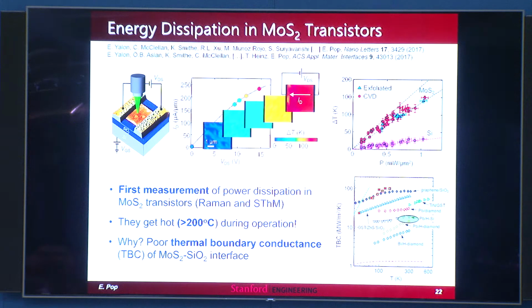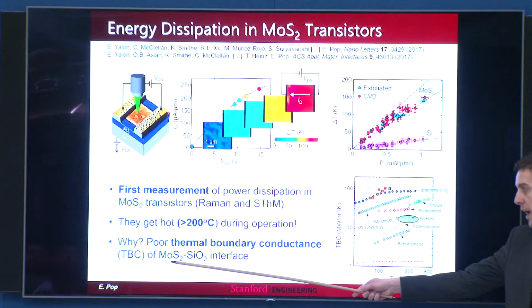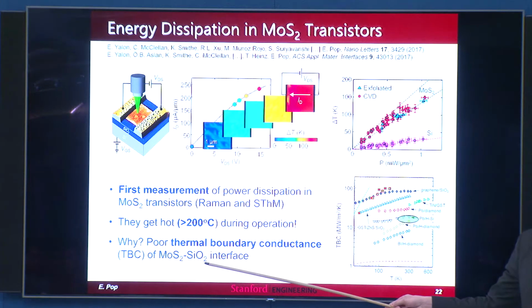But there's a more fundamental problem, which is that there's actually a very weak thermal boundary conductance across this weak van der Waals interface between the MoS2 and the SiO2. Remember I mentioned that the materials stick to things by weak van der Waals bonds. It turns out the weak van der Waals bonds are also bad for heat flow. So that is something to be a little bit concerned about in heat dissipation or power dissipation, anything based on these things. You'll see some ideas that we have with this, but it's something to be aware of. So to recap, van der Waals bonds: great for heterogeneous integration, bad for heat removal.